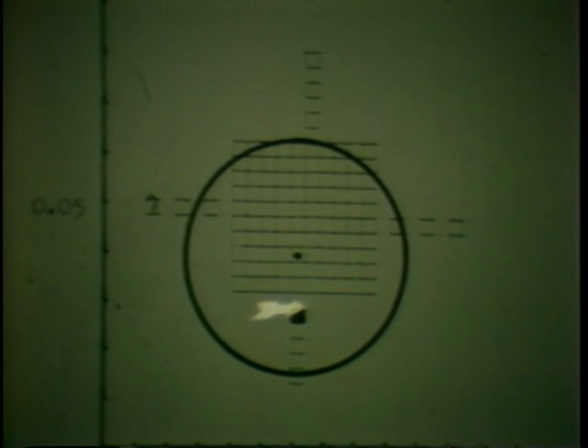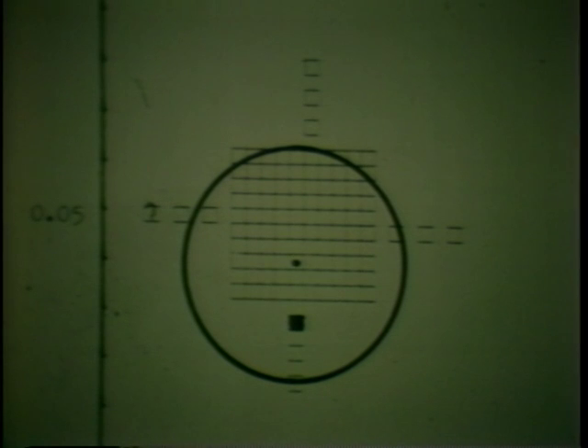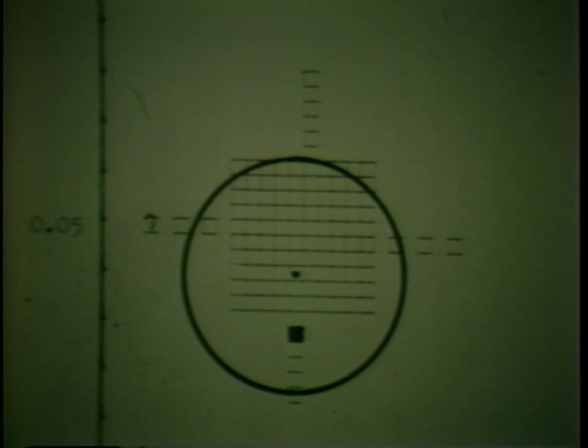Now, I only wish to show you that here is the 10 by 10 matrix of platinum squares, and out here are electrodes on which we are reducing ferric to ferrous chloride. At the same time, when at this segment, we are generating a hydrogen bubble. Now, the hydrogen is generated on a horizontal platinum surface, and it gets nice and big and fat. This bubble is 1.5 millimeters in diameter, which for electrolysis is a huge bubble. Electrolytic bubbles are small and nice, not these big floppy things like you see in distillation columns.